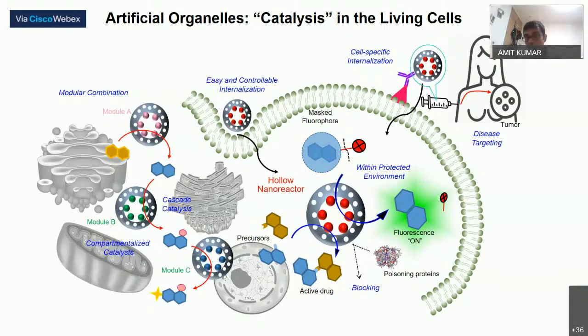Nanoreactors for this kind of biological applications face a very complex medium. It's not a normal reaction medium. So we have to be very careful in choosing the material we use for the nanoreactor synthesis. It should be highly biocompatible. The second requirement is that the catalytic sites should be modified inside the nanoreactor, and they should be surfactant free, and only the drug molecules or synthons should be allowed, and the proteins or other molecules should not interact with the catalytic sites.